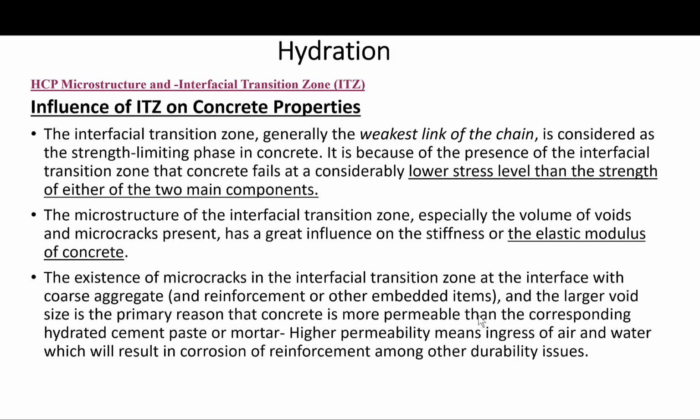So let's look again at more of the influence of the ITZ on concrete properties. The interfacial zone is generally the weakest link of the chain. It's considered the strength limiting phase in concrete. It is because of the presence of the interfacial zone that concrete fails at a considerably lower stress level than the strength of either of the two main components.